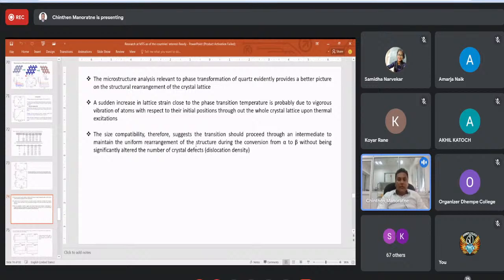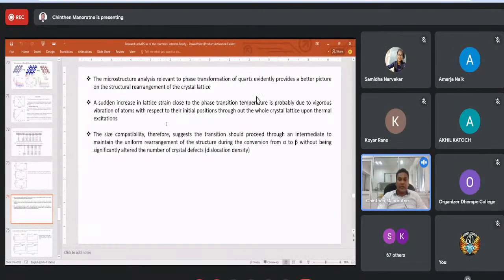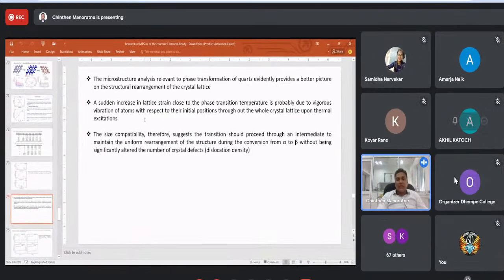Overall, it shows that microanalysis relevant to phase transformation of quartz evidently provides a better picture of the structural rearrangement of the crystal lattice. A sudden increase in lattice strain close to the phase transition temperature is probably due to vigorous vibration of atoms. The strain is due to vibration of atoms within the crystal structure, the unit cells. The size compatibility therefore suggests the transition should proceed through an intermediate to maintain the uniform arrangement of the structure during the conversion from alpha to beta without significantly altering the number of crystal defects.